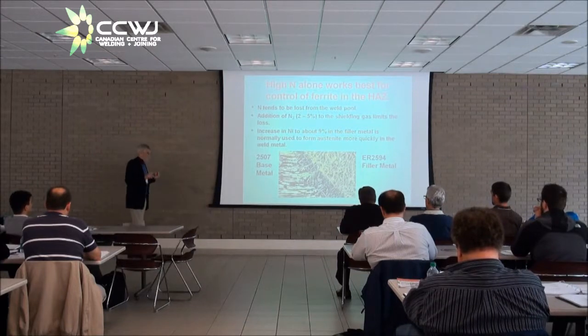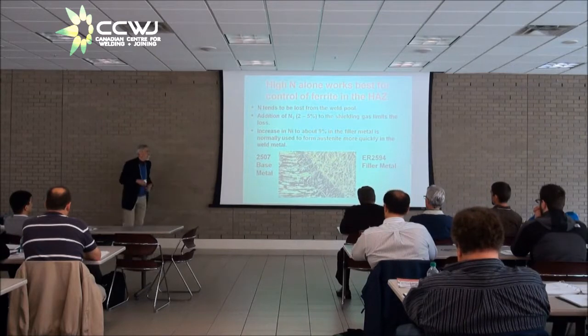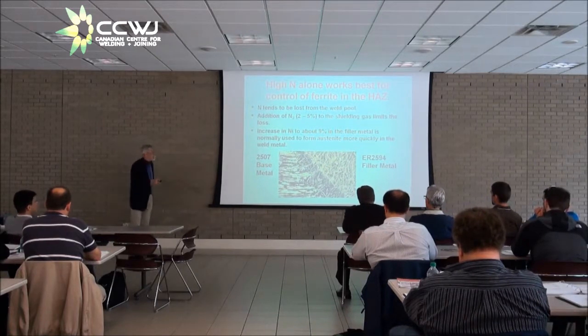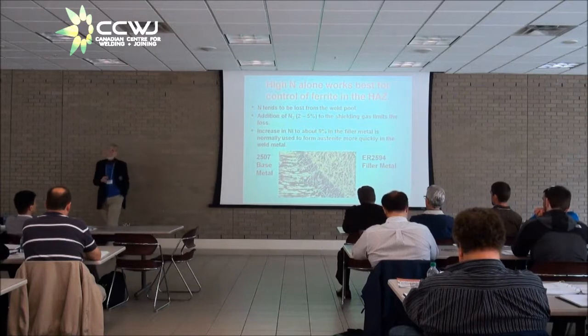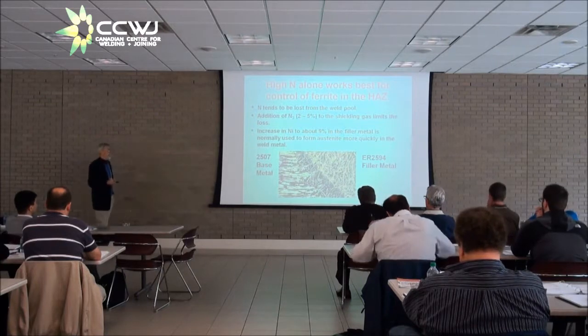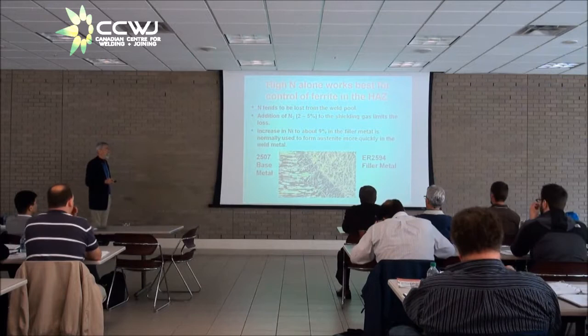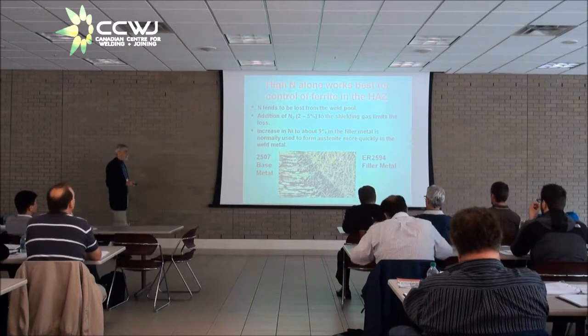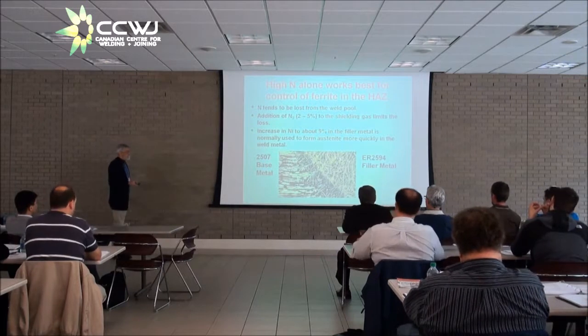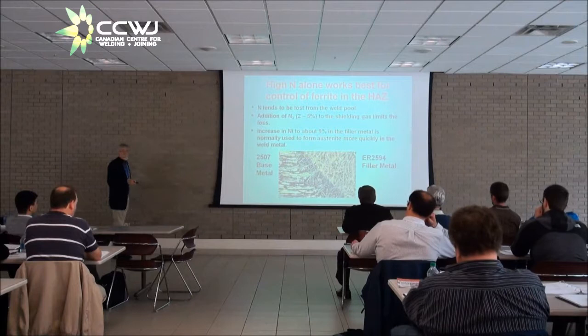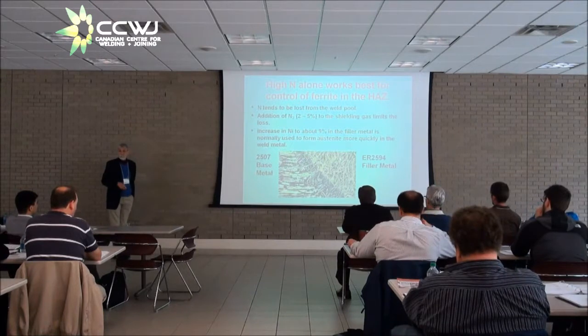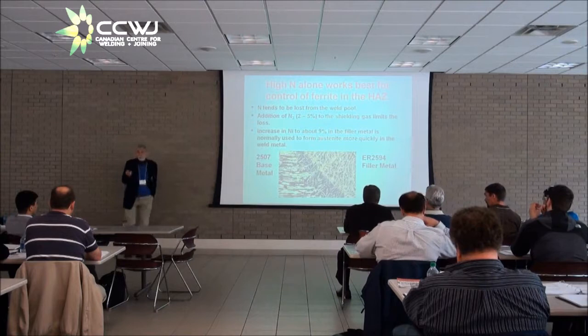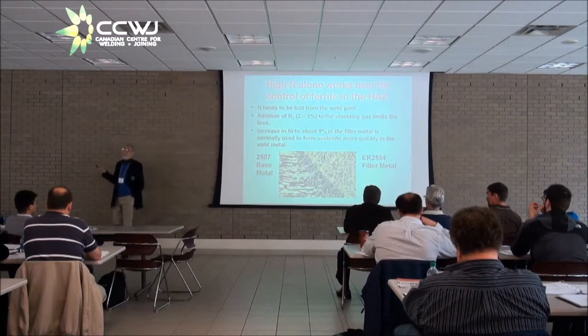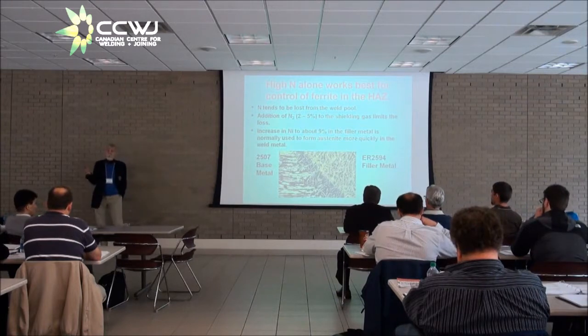In the filler metals, we still use the 9% nickel, as I mentioned. But this is the kind of microstructure you can expect if you add nitrogen to the shielding gas in a super duplex weld metal. This is the 2507 base material. Here you can see the heat affected zone has a little more ferrite in it than the base material. But there's enough austenite there to prevent any extensive nitride precipitation.